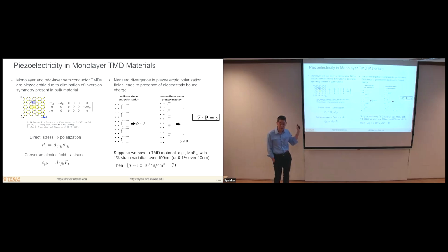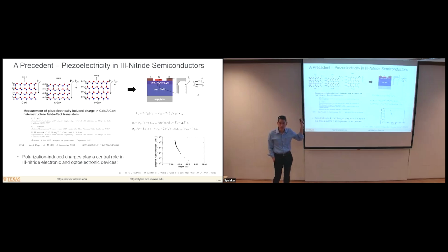So it turns out there's a precedent for piezoelectric effects being very important in understanding the behavior of certain classes of semiconductors. And this precedent actually comes from group 3 nitride semiconductors, which technologically now are of enormous importance. It's the basis for all solid state lighting that we have now, among other things. And in some work that my lab did back in the 1990s when we were at UC San Diego, we showed that piezoelectrically induced polarization in group 3 nitride heterostructures played an extremely important role in allowing two-dimensional electron gas structures to be realized with very high electron densities, because you would form a sheet of positive bound charge at this interface through actually a combination of piezoelectricity and spontaneous polarization.